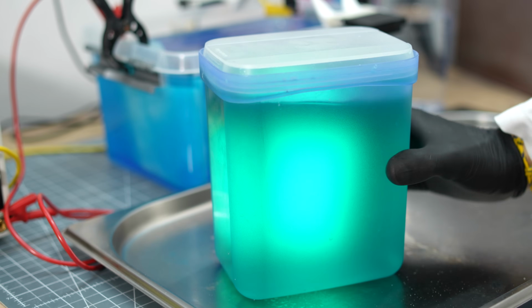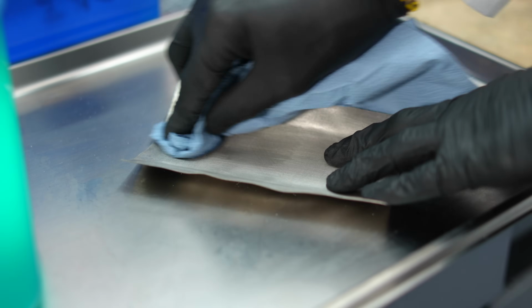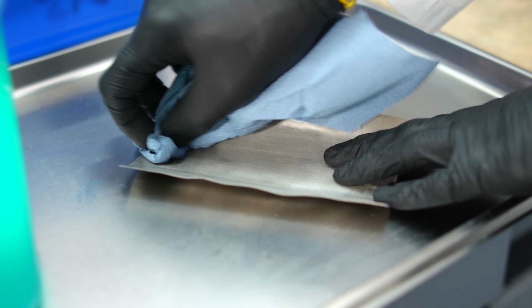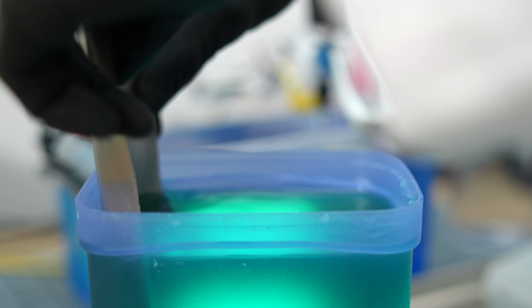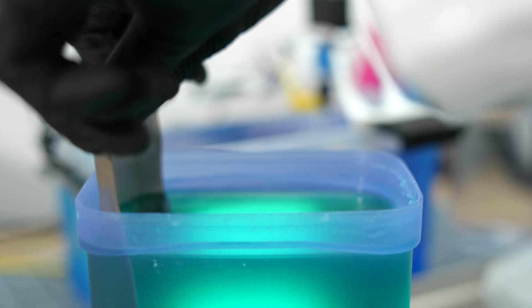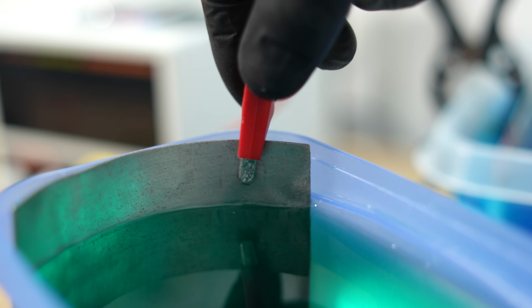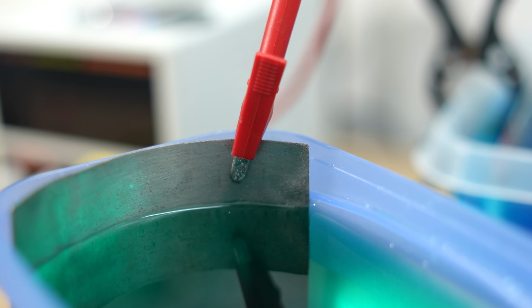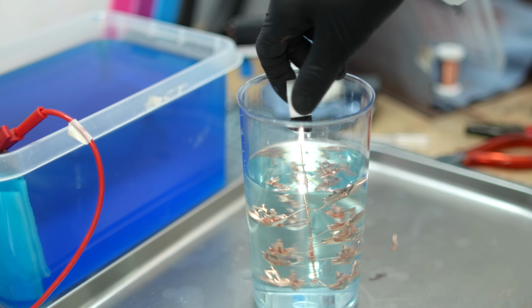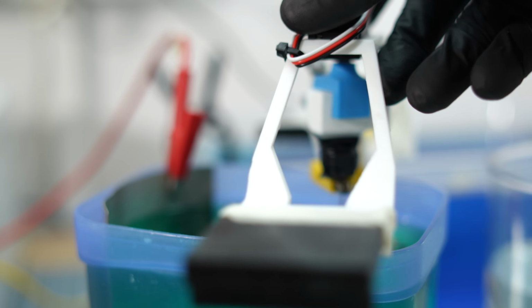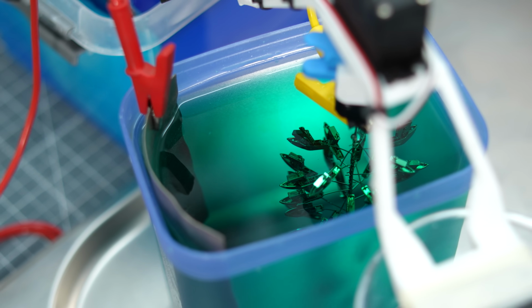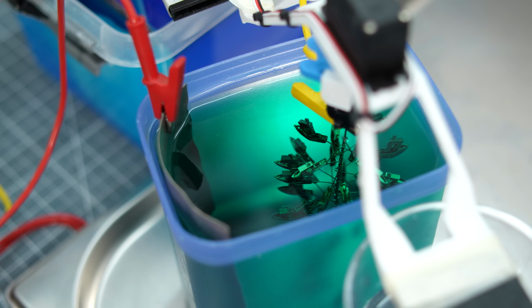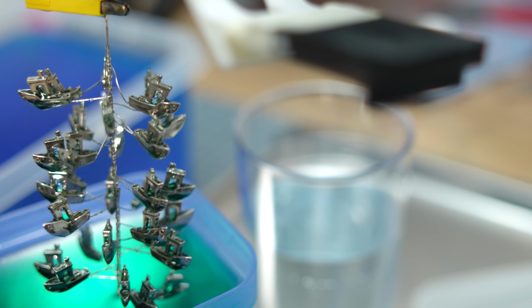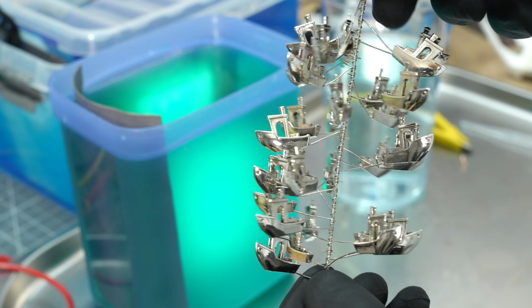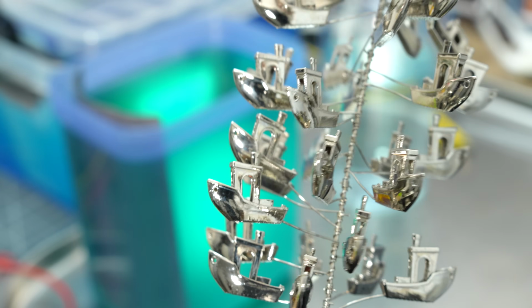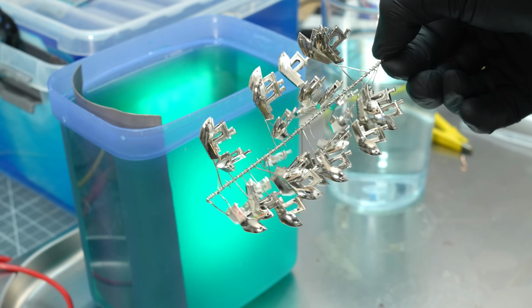Meanwhile, I'm already preparing the nickel bath. Here I need a nickel anode. It is placed in the bath and connected the same way as in the copper electrolyte. Nickel electrolyte is quite toxic, so one should be careful to wear proper personal protective equipment and ideally do it outdoors. Now I rinse the copper prints thoroughly in distilled water and immerse them in the nickel electrolyte. I let them coat for 5 minutes, using approximately 2 volts. Afterward, we have beautiful nickel benchies, the foundation for gilding. The nickel creates a diffusion barrier, preventing the gold from turning rosé gold over time.